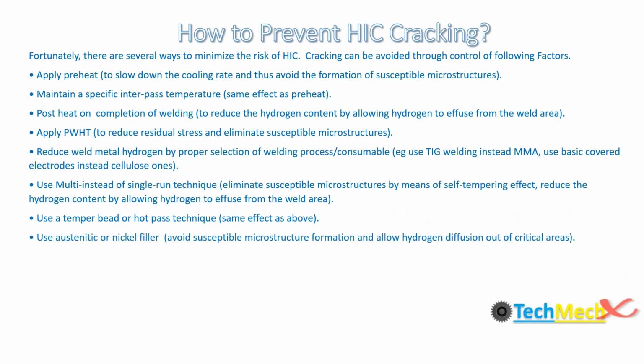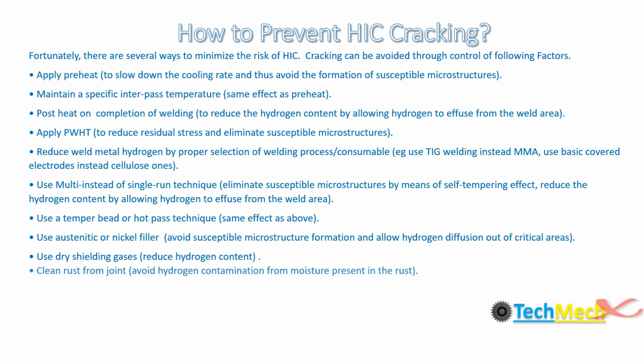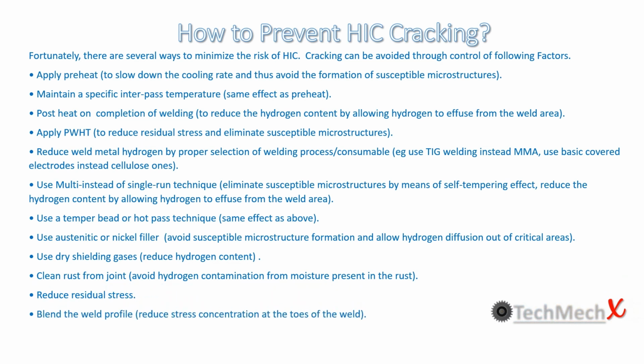Use austenitic or nickel filler to avoid susceptible microstructure formation and allow hydrogen diffusion out of the critical area. Use dry shielding gases to reduce hydrogen content. Clean rust from the joint to avoid hydrogen contamination from the moisture present in the rust. Reduce residual stresses: blend the weld profiles to reduce stress concentrations at the toe of the weld.